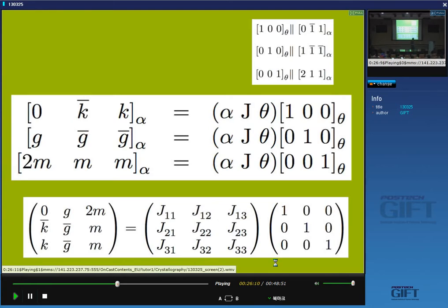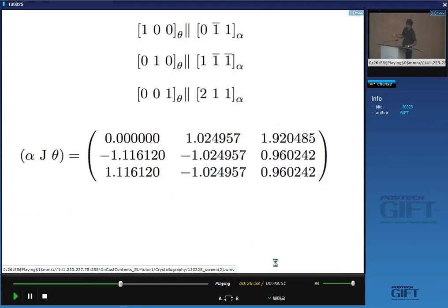with it to examine why this orientation relationship happens, what happens if a dislocation on a 0-1-1 plane wants to intersect the cementite, which plane will it come across? Will that dislocation be able to cut that particle, or will it have to bow around it? Because if there's no continuity of slip planes in the cementite and ferrite, then it will not be able to cut the cementite particle. So it's relevant in all your strengthening mechanisms and dislocation theory, etc. So that's quite a powerful result. Remember this when you're doing some transmission electron microscopy. Okay, so that's our coordinate transformation matrix between cementite and ferrite, just by taking that inverse.